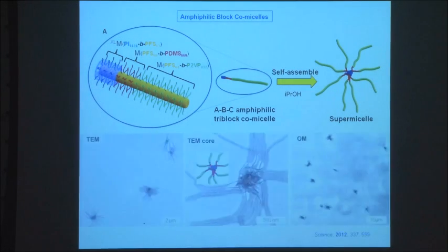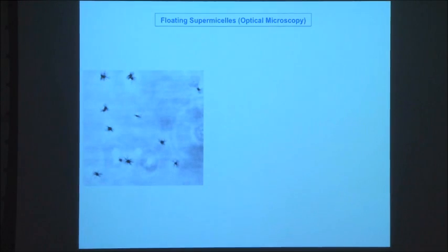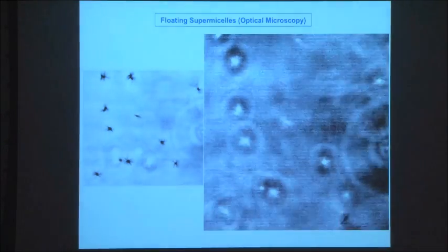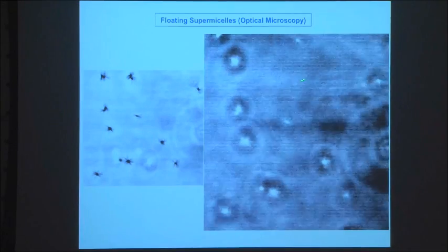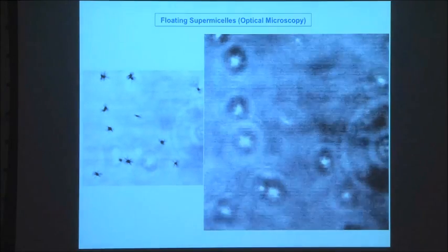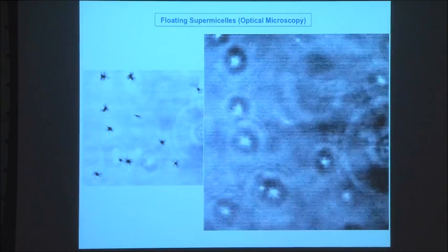And this actually works very nicely. So you can make these supermicelle structures. Here's the core of the structure, and you can actually visualize them by optical microscopy. They're sufficiently large, and they're actually very stable structures. You can pick them up with optical tweezers. That's something we've recently been able to do. And you can actually visualize them by video microscopy. So here they are in a thin film of solution, and you can see them every so often floating across the slide here. So these are quite interesting structures, and we're actually doing quite a lot of work with these right now.